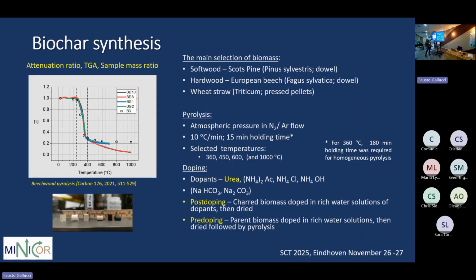Here we see a typical gravimetry curve, which is a mass ratio when you pyrolyze. From neutron attenuation, you see that it gets different here, and that is due to the hydrogen which is lost, because neutrons are very sensitive to hydrogen, which you will see later. The softwood in our case is Scots pine, the hardwood is European beech, and then wheat straw. These are woods that are of interest in our group.